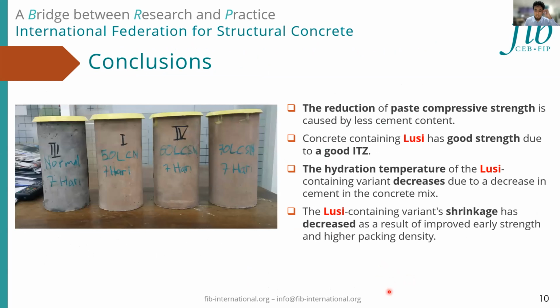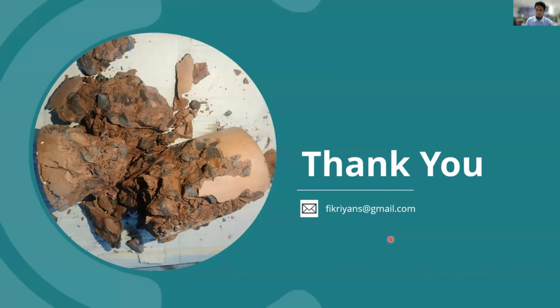And from the result that has been presented, it can be inferred that the reduction of paste compressive strength is caused by less cement content. And the concrete containing Lusi has good strength due to a good ITZ. The third, the hydration temperature of the Lusi containing variant decreases due to a decrease in cement in the concrete mix. The Lusi containing variant's shrinkage has decreased as a result of improved early strength and a higher packing density. I think that's my presentation.